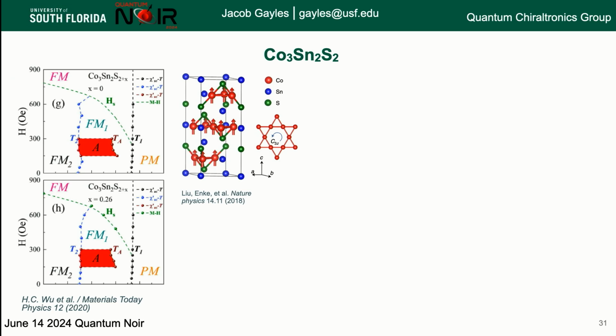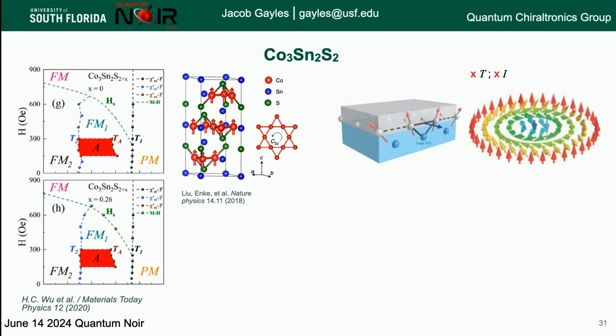However, recently, some people have found this red spot here, which is called the A phase, or anomalous phase, where they look at the magnetic susceptibility. That means the change in the magnetization with the change in the external magnetic field. And they do this with AC fields and DC fields. They find this pocket where it looks like there's a magnetic texture. So what happened there?